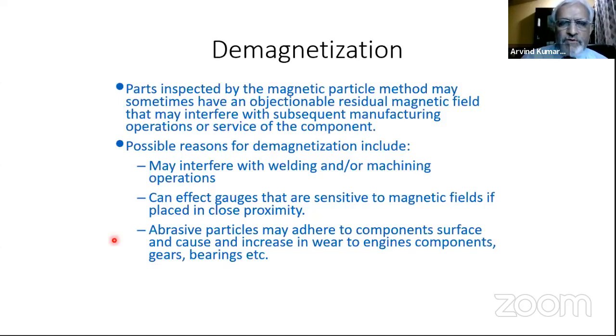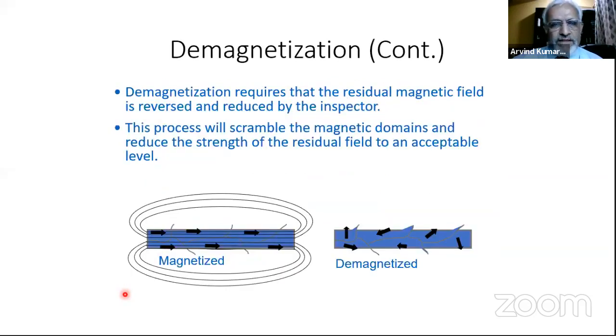Now, you may be required to demagnetize a part after the test has been done. May not be always, but certain applications would require demagnetization. If your subsequent operation is likely to be affected by the magnetic field, then you have to do a demagnetization. That means bring the part to the original condition by removing the entire magnetic field. Generally after demagnetization, in pipelines, up to 25 Gauss strength of magnetic field is acceptable. But the best is, if you do not know how much to accept, restrict it to about 5 Gauss, and you can demagnetize.